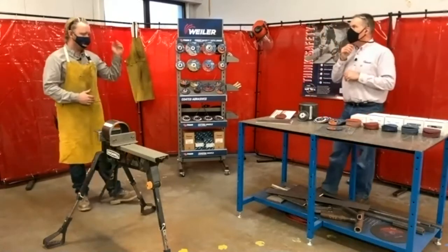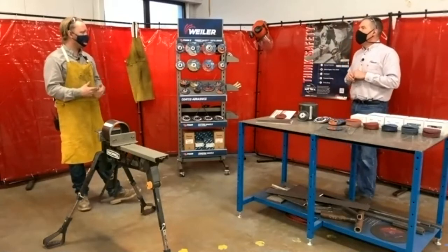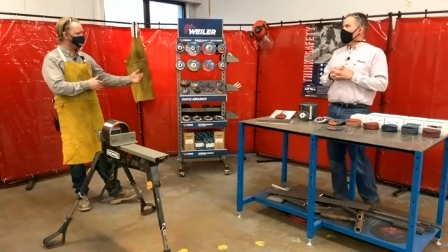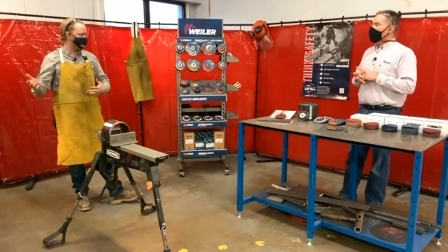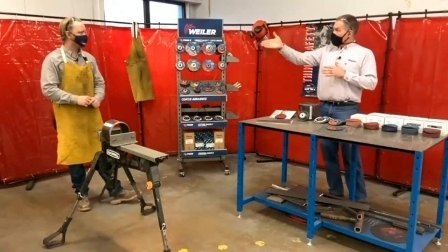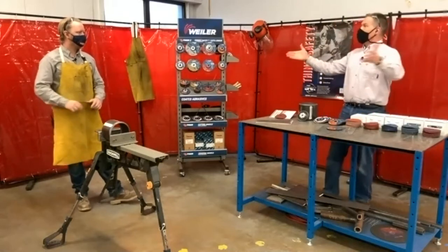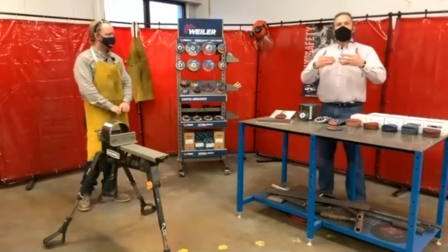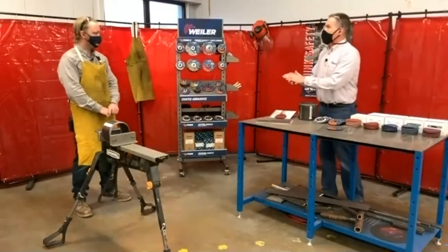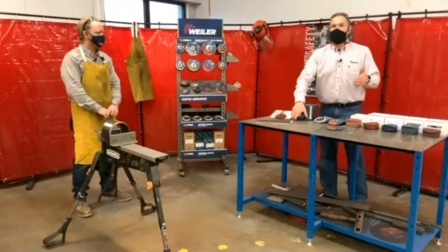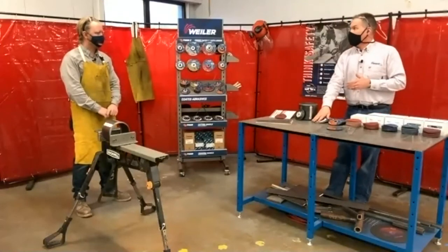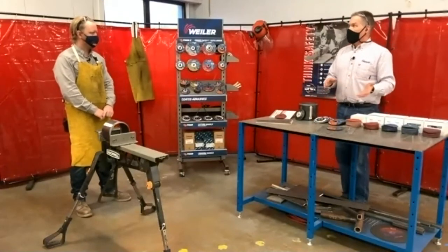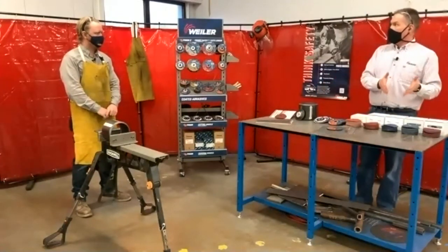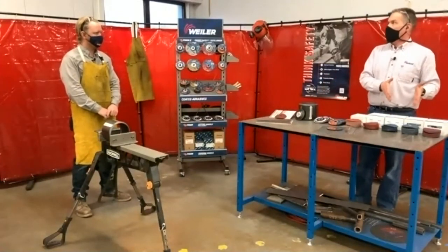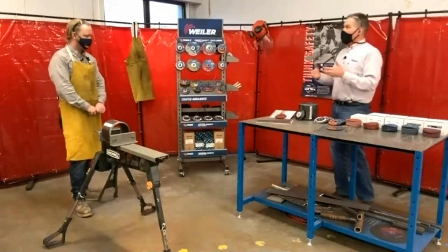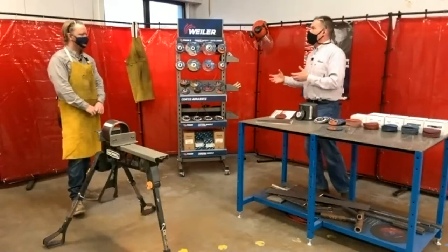Right, and the same aspect too is you could bear down on an 80 grit and have it last a very short amount of time, or be really light with the 36 grit and it could last an extended period of time. So you bring up a phenomenal point there, and one last thing to consider is that because of the focused aggression on the backside, if you're using a 40 grit flap disc in particular, you may find that you actually get higher aggression and work done faster with a 60 grit resin fiber disc, right? Because again, it's all about the focused cutters onto the work surface.